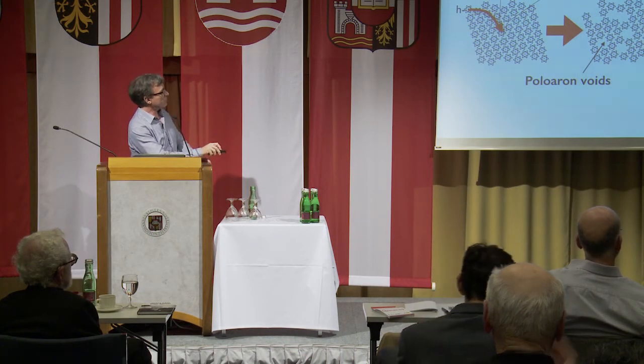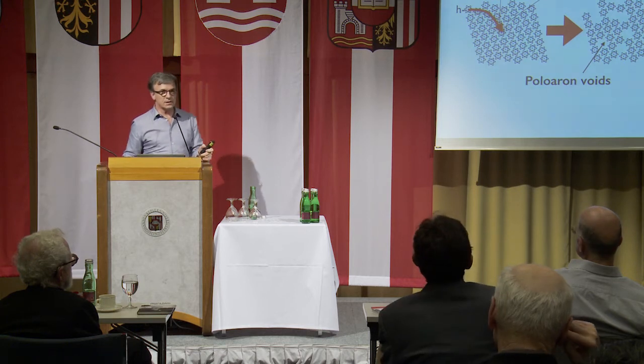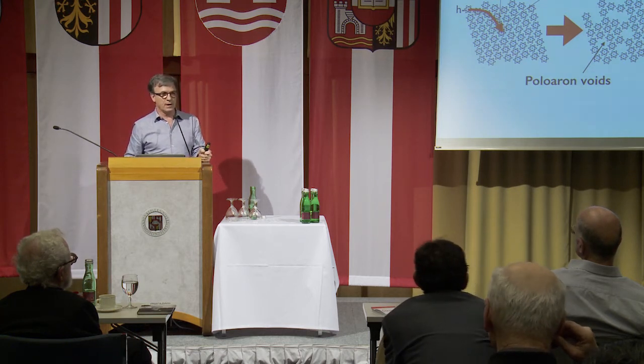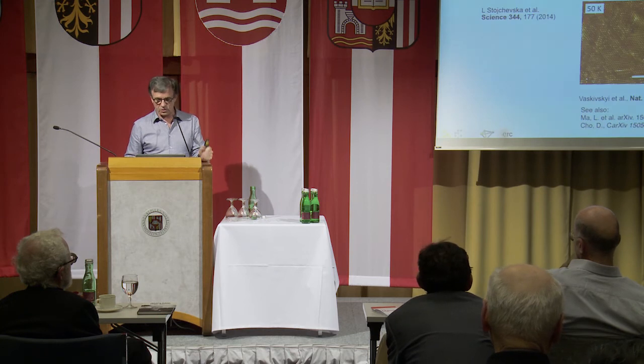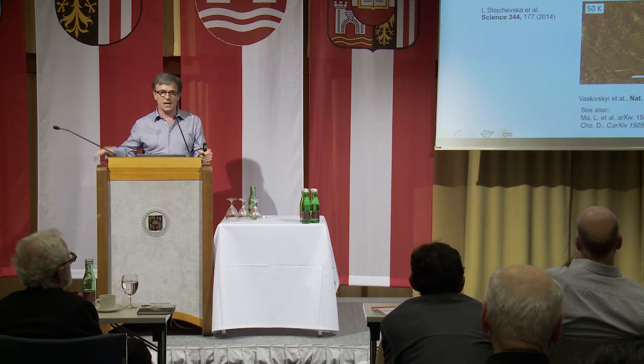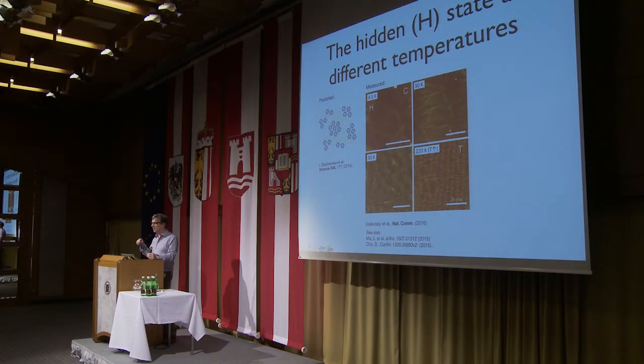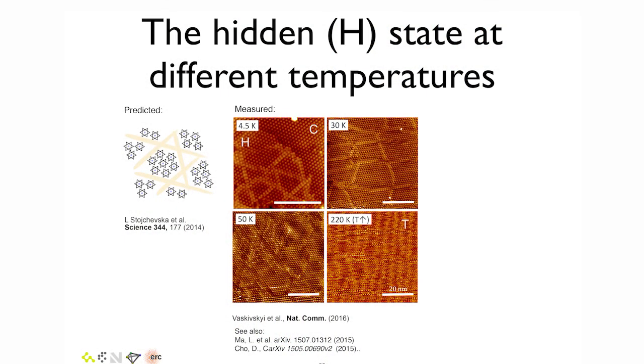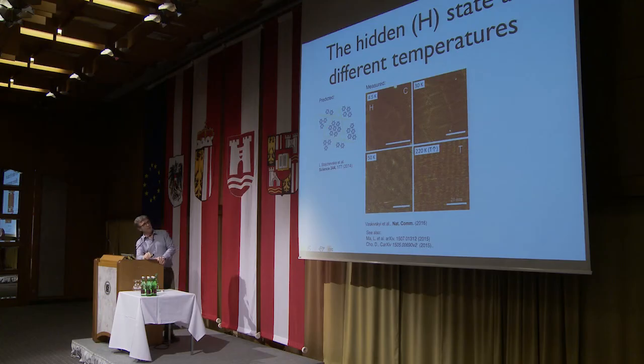Okay, now that was published in this paper 2 years ago, and since then we did the obvious thing, and that is to look at the crystal structure, the STM images of switched crystals. So remember the one that I showed you earlier? It was nice and uniform. There's basically polarons beautifully in a hexagonal pattern. Well, here you see exactly the sort of features that we predicted in our original paper, which we were, I must say, very happy about.